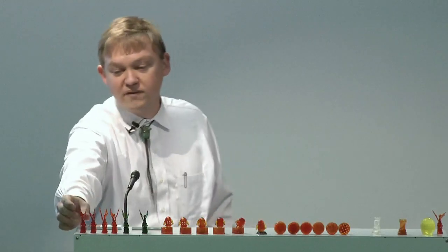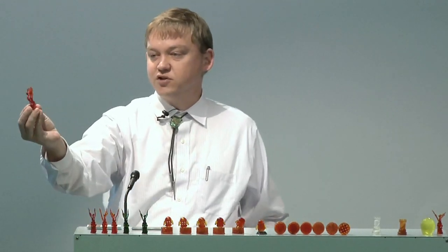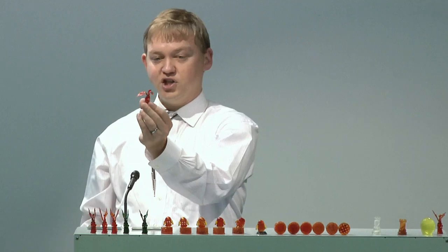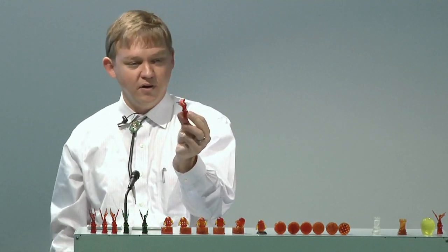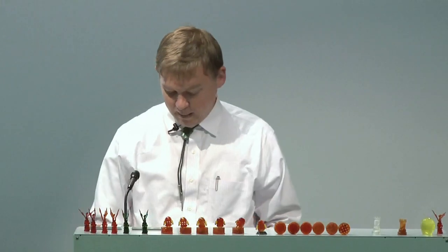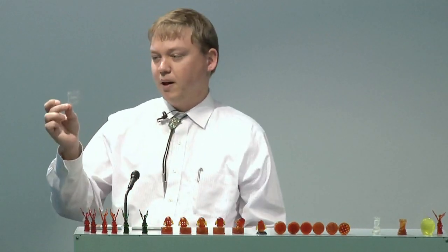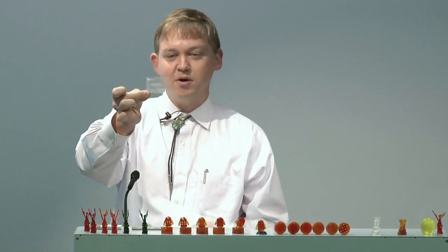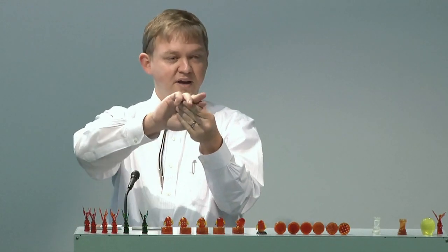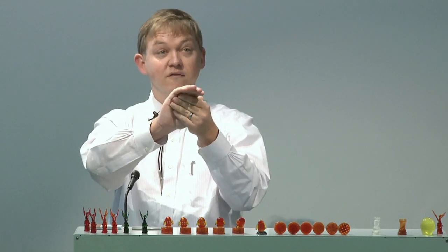Here are some dragons we've also printed — you can get a sense of the feature sizes we achieve. These belong to a class of materials close to shape memory polymers called viscoelastomers, which are in a transition state. When I deform the dragon's wings, they slowly recover. Here's a little business card made of a shape memory polymer — it's stiff and glassy at room temperature with a modulus of two gigapascals, just like plexiglass.